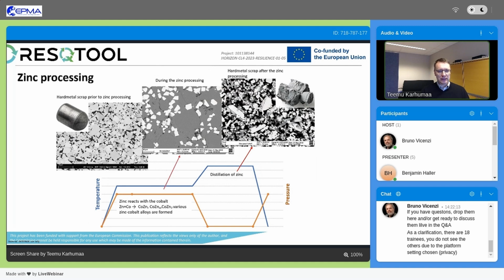And once the zinc is removed from this phase of cobalt and zinc, the leaving zinc leaves empty space between the tungsten carbide grains. So in the final part, there are tungsten carbide grains loosely touching each other, and some cobalt particles in between. And this can be easily ground to powder.